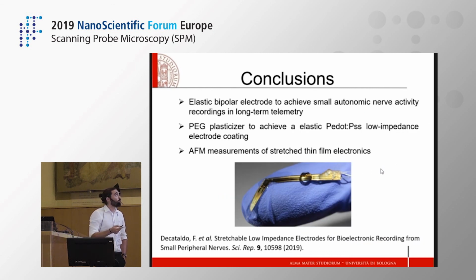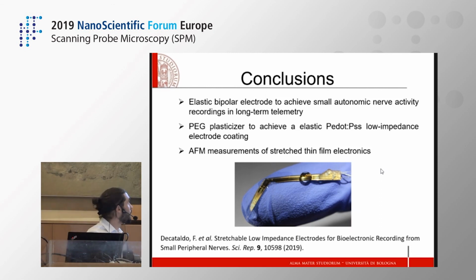So to conclude, we managed to realize an elastic bipolar electrode in order to achieve a good signal of the nerve activity in long-term recording. And in particular, we added the PEG plasticizer in order to improve the elasticity of our PEDOT:PSS low-impedance electrode. Finally, AFM measurements were performed on stretched thin films in liquid in order to mimic the biological implant itself. And this allowed us to say that basically with the PEG, we have an altered growth mechanism that leads to a lower Young modulus and a more elastic film.